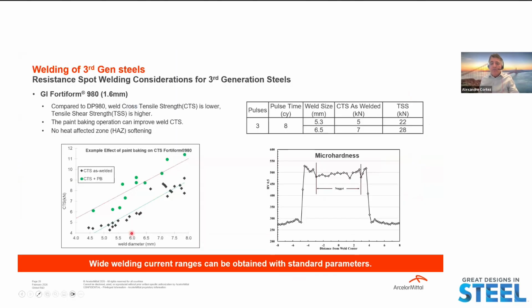Okay, now we will switch to joining and welding considerations for Gen 3. First, I would like to highlight the GI Fortiform 980 product. Compared with the DP980, weld cross tensile strength is lower and the tensile shear strength is higher. I would like to highlight for this product that the paint baking operation can improve weld CTS, as you can see in the graphic here, CTS without paint baking and CTS with paint baking over here, with the increase in strength. And here we show that we use pulses in welding, giving a good weld nugget size, and also achieve the strength for CTS and TSS.